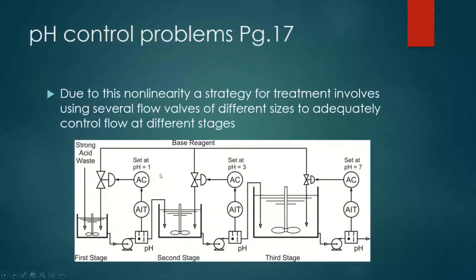So one of the applications in industry that's used to do this is something like we see here in this diagram, where we have an injection station that uses different sized valves. You see a big valve here for a pH at one, a middle sized valve here when the pH is near three, and then a much smaller valve when we're approaching the pH of seven. So this effectively will introduce lots in the beginning, reducing it as we get closer, and then finally just allowing a trickle of our reagents in the final stages as we approach our set point. So that's one of the process ways that we get around that nonlinearity that's associated with pH.